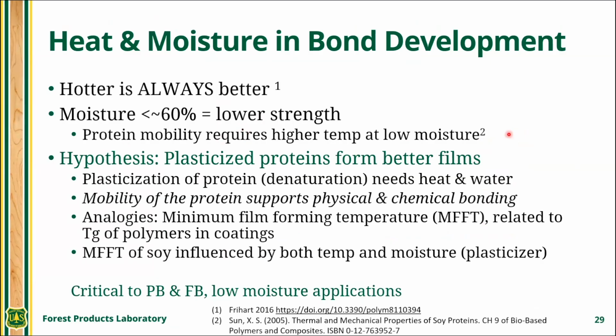Note that it's very well documented that protein mobility requires a higher temperature if there's less moisture present. So when we talk about the denaturation temperature of a protein, that's under the assumption that it's under saturated water conditions, very high water. If the water content goes down, the denaturation temperature goes up. And denaturation is the ability of the protein molecule to move on a large scale. It's essentially a glass transition. And water is the plasticizer that allows this polymer to go through a glass transition at a lower temperature. If you're limiting water, you need more heat to go through the glass transition, which we call denaturation in proteins.